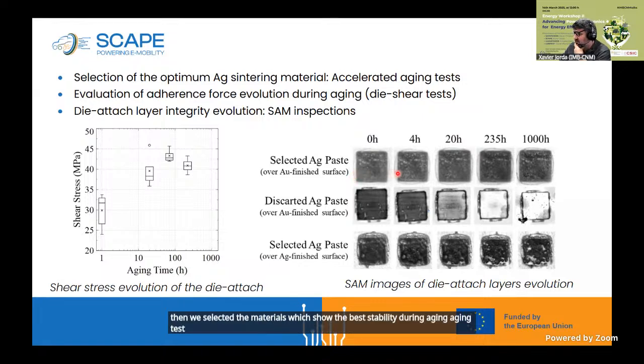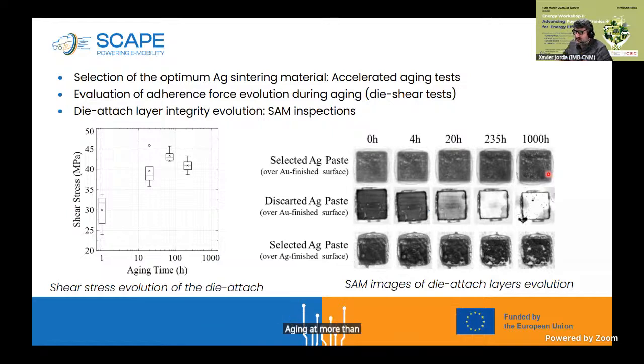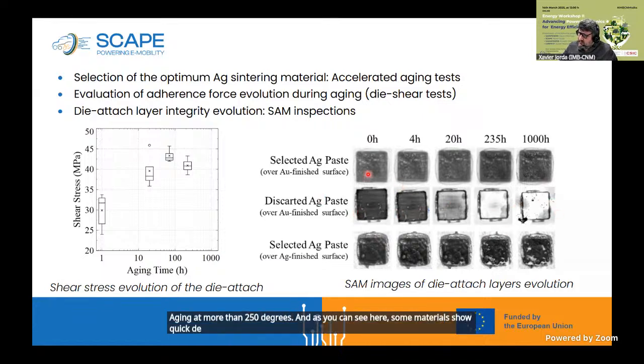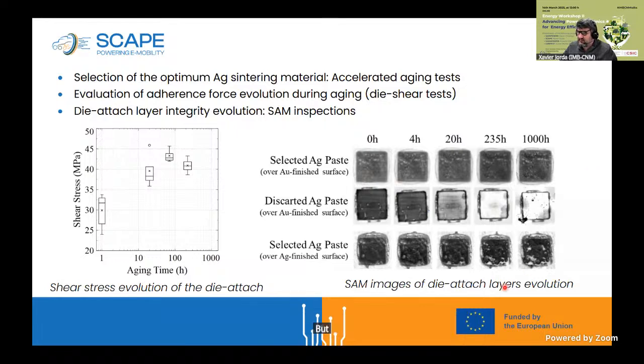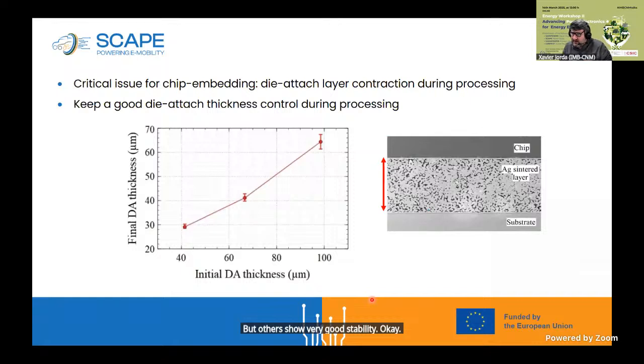You can see here the acoustic images of the die attach of one device after 1,000 hours aging at more than 250 degrees C. And as you can see here, some materials show quick degradation, but others show very good stability, okay? And finally, another aspect which is very, very relevant is to control the thickness of this die attach